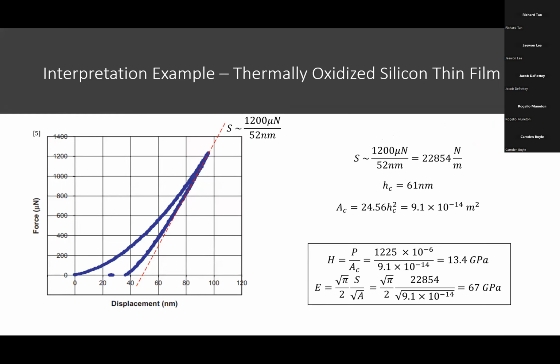This was 1200 micronewtons divided by 52 nanometers, yielding 22,854 newtons per meter for the unloading stiffness. The paper gave a contact height of 61 nanometers, and using that contact height with the formula for the contact area for a Berkovich tip—24.56 times the contact height squared—yields 9.1 times 10 to the negative 14 meters squared.